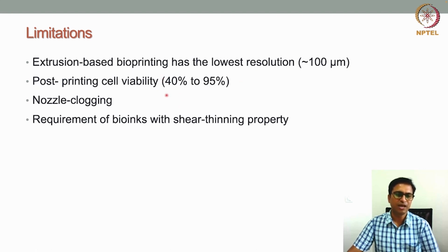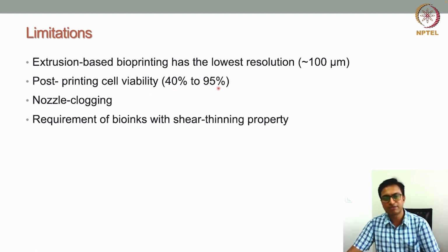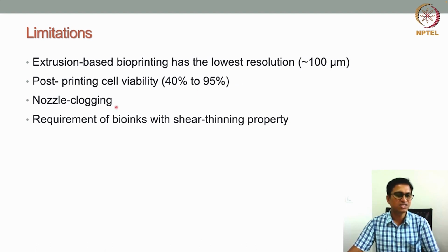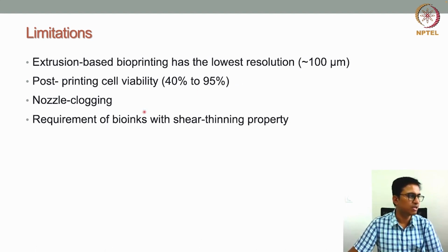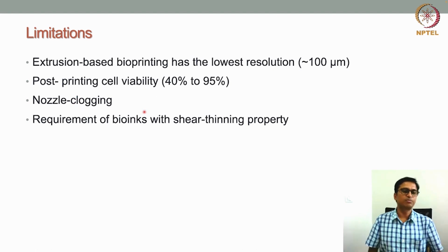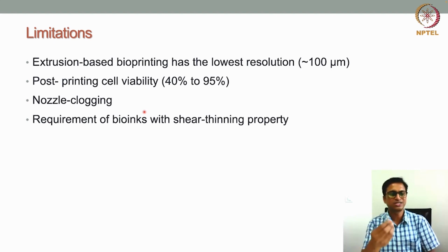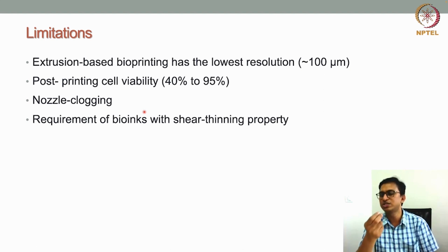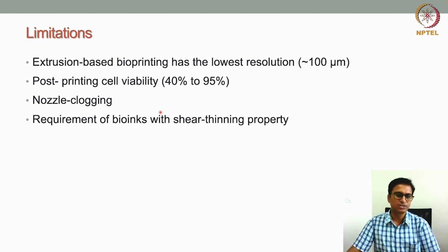Researchers have reported cell viability from 40 to 95 percent, depending upon the process parameters, and also depending upon the hydrogel and the viscosity of the hydrogel. Another thing, because this is a nozzle based system, is that nozzle clogging can be a problem, so it has to be taken care of during the process. Nozzle clogging is when the nozzle is clogged due to the material, or if you have some particles within your hydrogel system, that can clog the nozzle. So nozzle clogging is an important challenge for this extrusion based bioprinting strategy, and you need to take care of it.